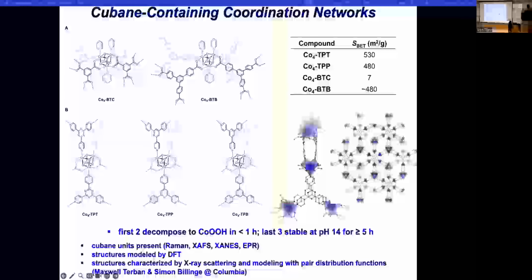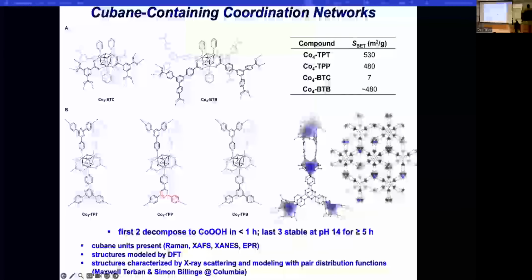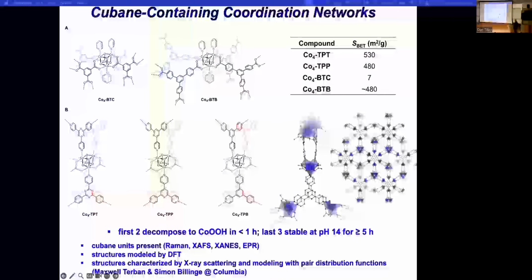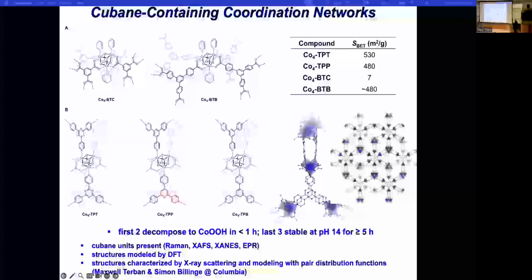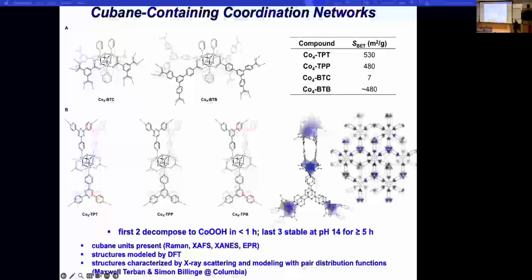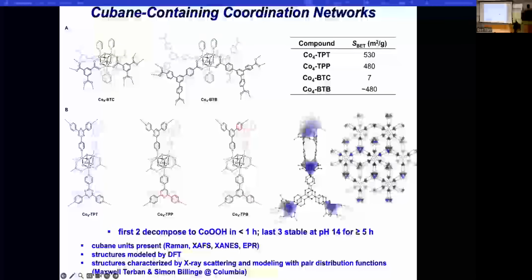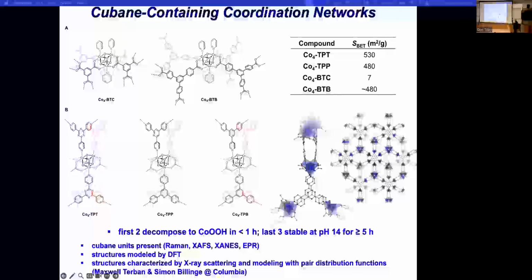Okay, here's another way to stabilize the cube. It's to put it in a rigid coordination network. And so we were able to do that using tritopic, tripyridyl monomer units. And you see five of the MOF type structures that we made this way here. The ones that are linked, actually two of them are linked through carboxylates. Those give high surface areas, but they're not good because the carboxylates are too labile. So the three down here below are ones that we've looked at more in terms of stabilization and further mechanistic studies.